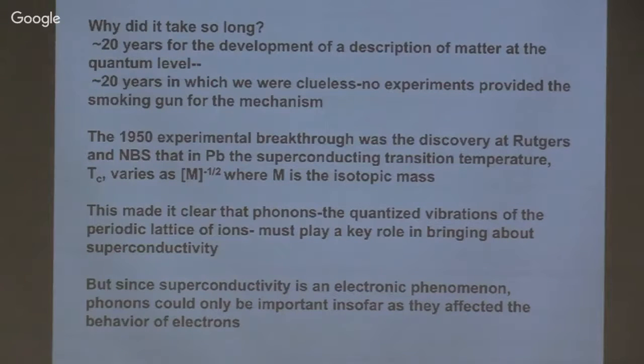Well, for 20 years, we didn't have a good quantum theory of matter, but we did after 20 years. It still took another 20-plus years before we had a smoking gun. And it came from experiment. The experiments on the isotope effect showed that the transition temperature depended on the mass of the ions in the metal that you were studying. And it goes as roughly 1 over the square root of mass, and that says, okay, the phonons, the elementary excitations of the lattice, must be involved somehow. But the question is how do phonons influence the properties of the electrons?